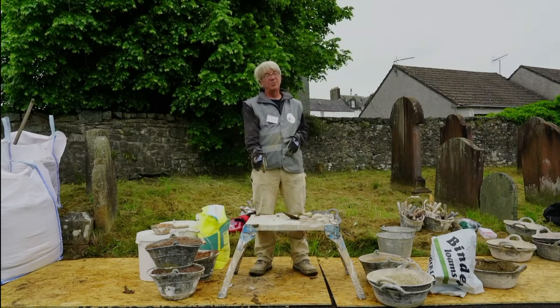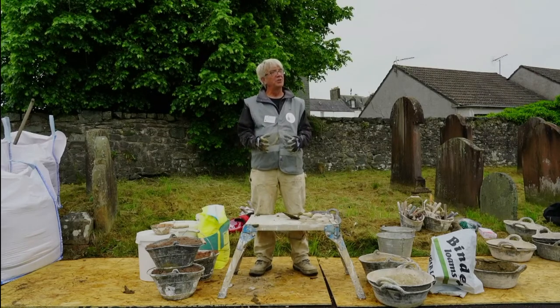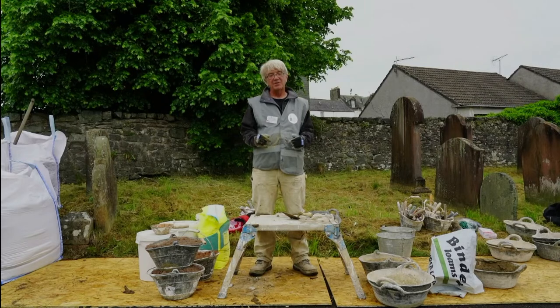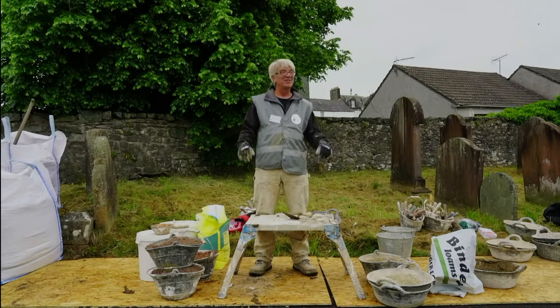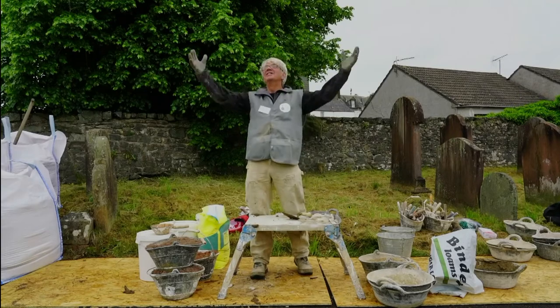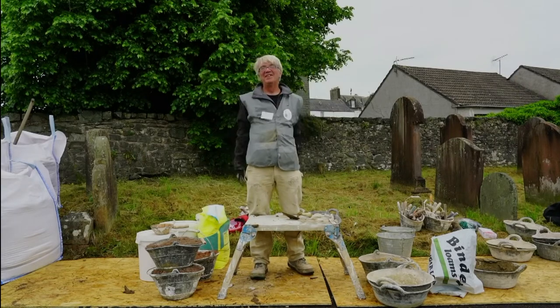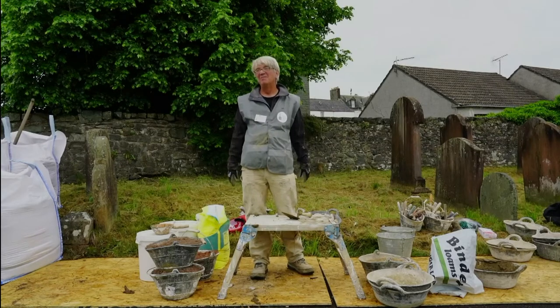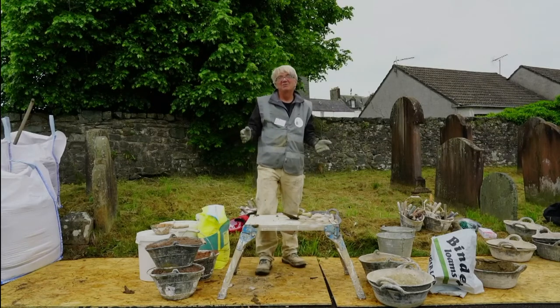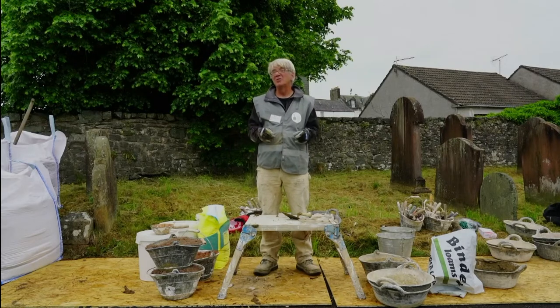So that went down to the bottom, obviously, and started to slake. And obviously, it was then getting very hot down there because there wasn't enough water to slake it. Plus, because it's powder, the air couldn't get out. The steam that was being generated couldn't escape. So they filmed this. They stood around watching this and thinking, oh, no. And then it suddenly goes, bang! And the whole top of the lime just flew off because they'd made it like a pressure cooker. That's quite hazardous. But only because they didn't know what they were doing.